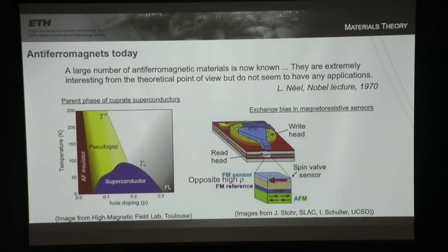And so in order to sense the orientation of a field with this sensor layer, of course, the reference layer has to not switch too, right? If they both switch, they'd always be parallel, and we wouldn't have any mechanism for the sensing. And the thing that stops it switching is the antiferromagnet. And so here's a cartoon of how that works. It's called exchange bias coupling.